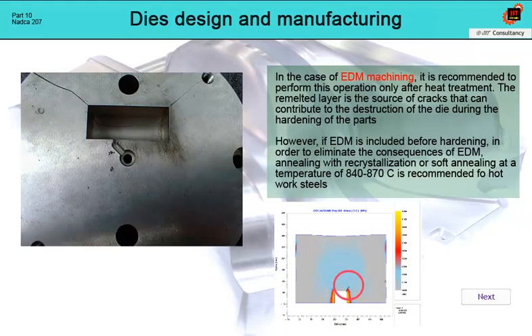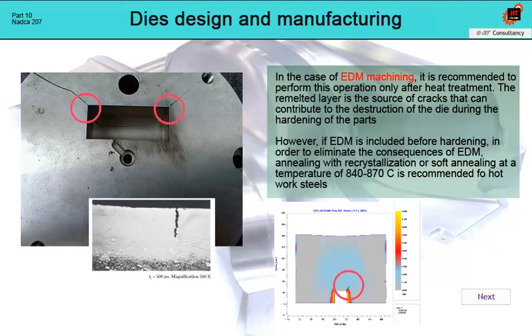A special case is the application of electro-erosive machining. It is known that due to an electric discharge, a thin layer of remelted material is formed on the surface. It is brittle and hard and can be a source of cracks. If EDM is applied before hardening, the layer must be treated at least by annealing to remove stress, but even better by soft annealing or annealing with recrystallization.